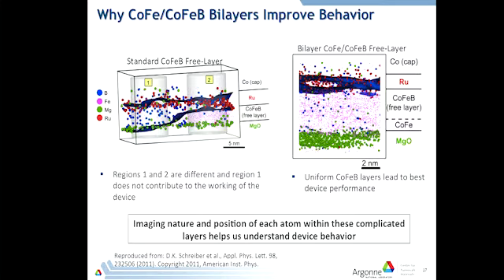So it turns out what we used was called an atom probe tomograph, and what that allows us to do is basically at the atomic scale level identify what the atoms are and where they're sitting in 3 dimensions. And so we can actually go in and kind of count the number of atoms, quite literally, that we have in our sample. And in this case, what we were counting are these blue atoms, the boron atoms, because it turns out that those are actually the ones that really critically control whether a device is good or not, by the way that they move around when you heat the structure up.